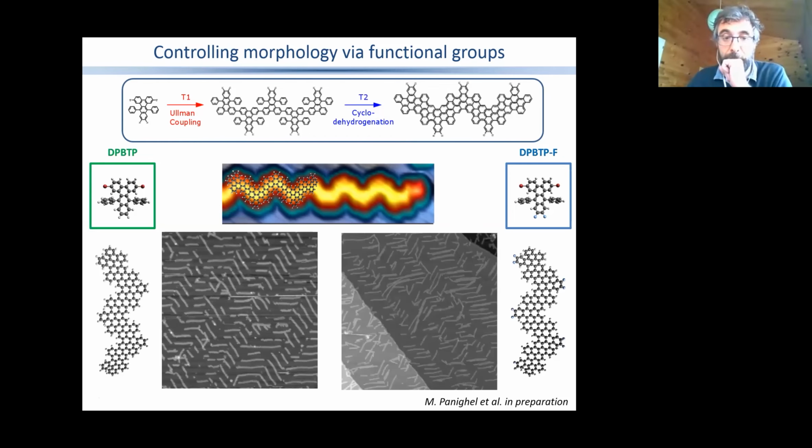And that means that when we grow the nanoribbons, following the same reactions as I told you before, the nanoribbons will try to be located on these rails, on these FCC rails, tracks of the zigzag herringbone reconstruction. So if you want to grow this kind of ordered structures, it's good, but you are again limited by the length here, because the periodicity of these zigzag structures is limited, okay? And it's of a few nanometers. I think it's in the order of 10 nanometers.